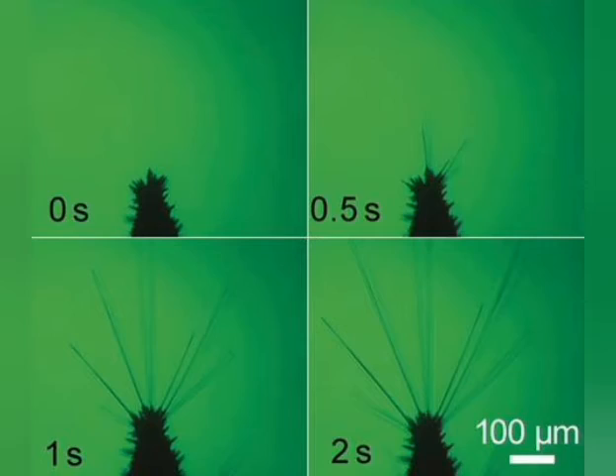The fibers were grown at minus 50 degrees Celsius from the tip of a tungsten needle. By applying a voltage to the needle, the team accelerated diffusion of gaseous water molecules to the needle's tip, growing fibers over 400 micrometers long in just two seconds.